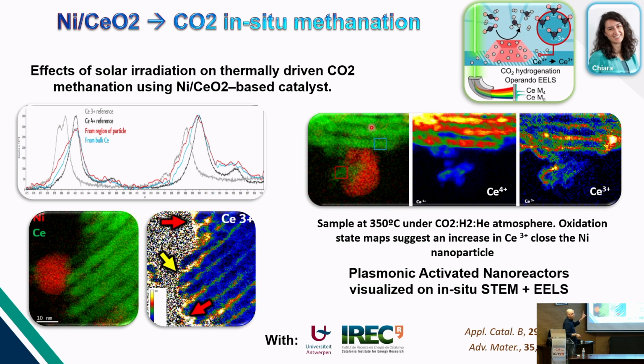because here we couldn't illuminate the sample. So what we were doing is, instead of illuminating, we were heating the sample at similar temperature of what we thought it was the one provoked by the plasmons. And in this case, what you see is that the reduction of the ceria is exactly around the parts where the nanoparticle is.